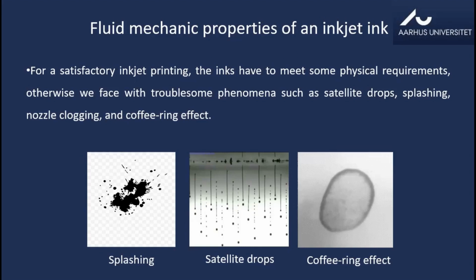And this is a common problem because, again, as I said, these droplets that you are printing need to impact the surface and you need to evaporate this solvent. And normally we are printing at room temperature. Now, depending on your room temperature, whether you are in Denmark or in Singapore, your temperature is going to be different. And when this temperature is different, evaporation rates might be different. But it's not too much of a difference, but there is going to be a difference if you don't provide the right environment. And you would end up forming these coffee ring effects if you are printing patterns onto your substrate. That means everything is being pushed to the side.